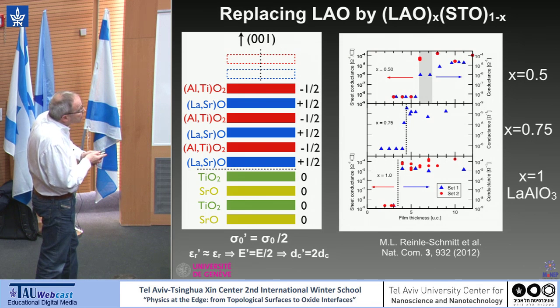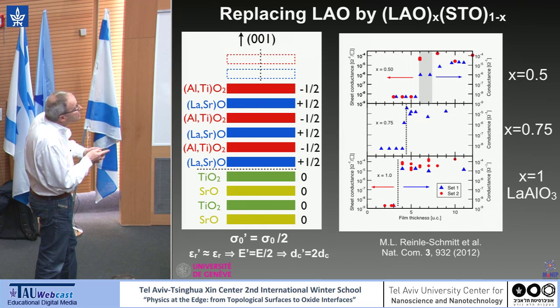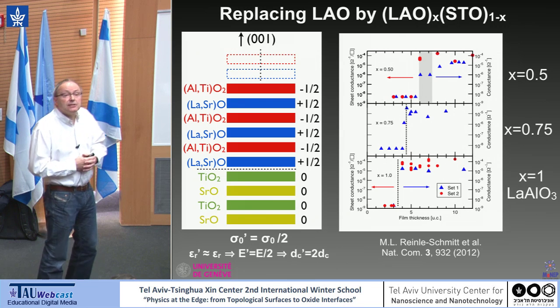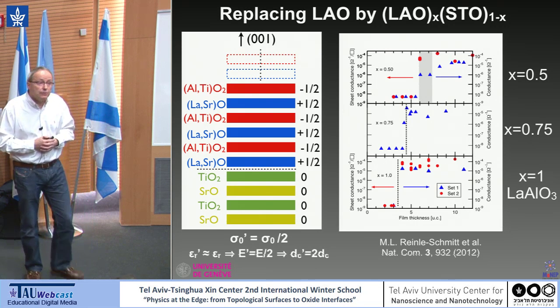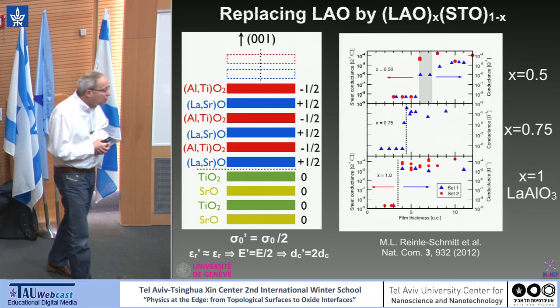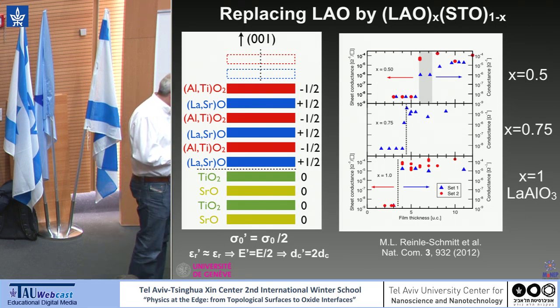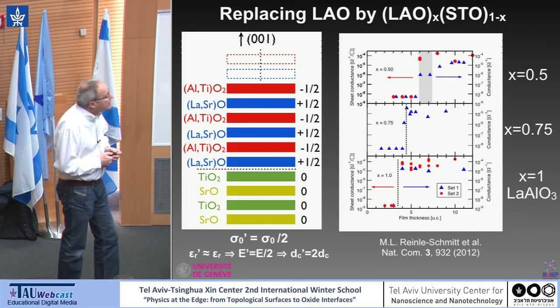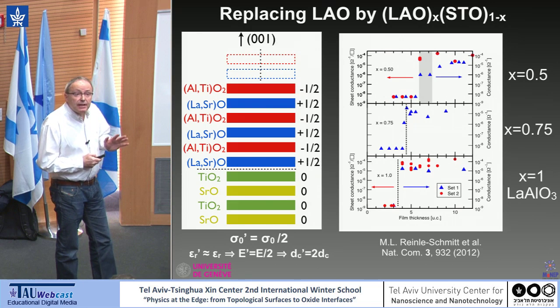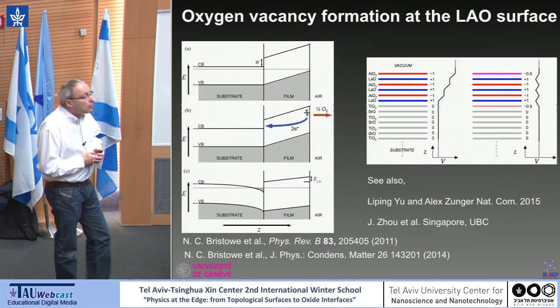This is the sheet conductance versus film thickness. This is lanthanum aluminate. This is the step I was just discussing. And if you look at this 0.5 alloy, you see that this critical thickness is shifted maybe to 7 unit cells. So experiments which are in line with this polar catastrophe model. Let me end by mentioning that there is a lot of ongoing work on this.